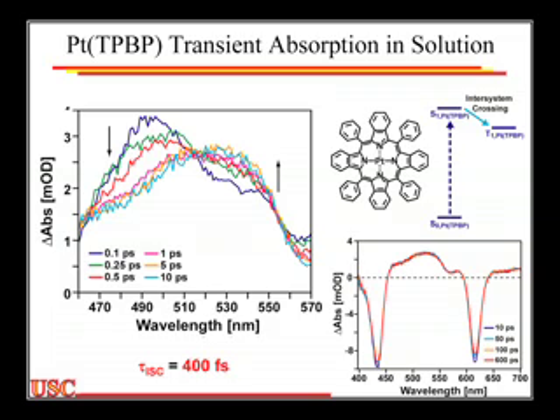So if I wait 10 picoseconds, it seems to have evolved. If I blow the spectrum up just in that part, you can see that over the time course of 10 picoseconds, this band bleaches and this band grows. I didn't know I could do that. That's pretty good. And so from this I can derive the time constant for those processes. The time constant is about 400 femtoseconds. That is the intersystem crossing.